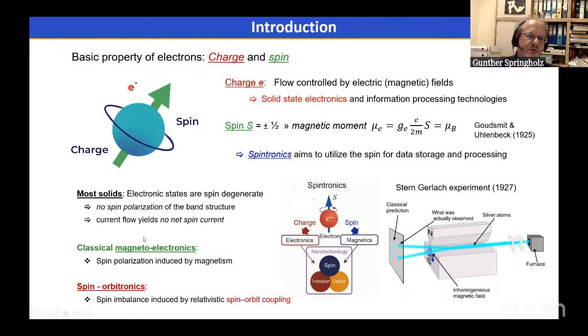So to work around this, classical magnetoelectronics utilize magnetic materials to obtain a spin polarization. So that is one direction. The other direction is based on spin-orbit coupling, which is a relativistic effect. And this spin-orbit coupling usually can induce a spin imbalance in various properties of the system, be it in the spin polarization of the band structure, but also an imbalance in the flow of electrons with spins in the system. So in essence, as shown in this cartoon, spintronics tries to unite these charge and spin properties and create new functionalities by this combination.